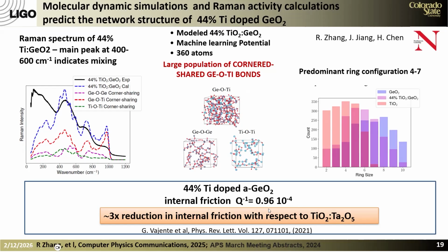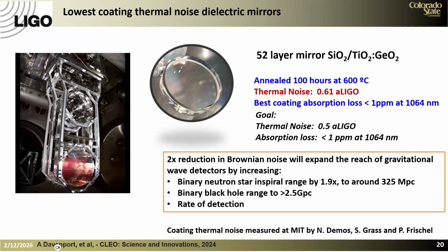And so when we anneal this material, we can actually get an internal friction that is just as low as Germania. And this value of internal friction is such that it is about a 3x reduction with respect to titania tantalum. So next LIGO coatings call for a reduction of approximately 4 in the internal friction, and which results in approximately a reduction of 2 in the coating Brownian thermal noise.